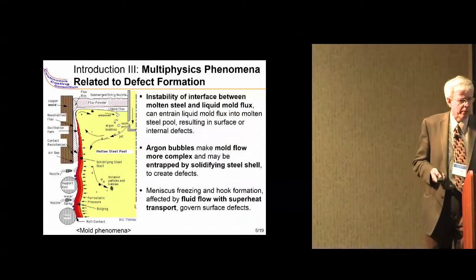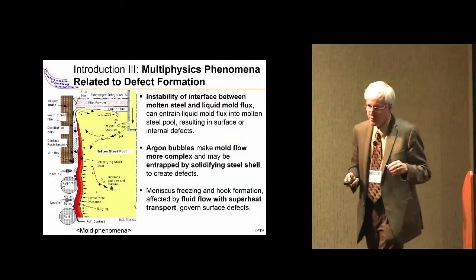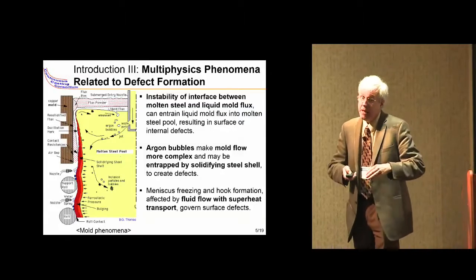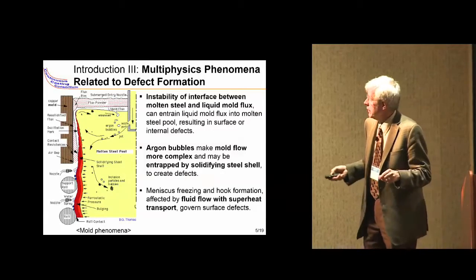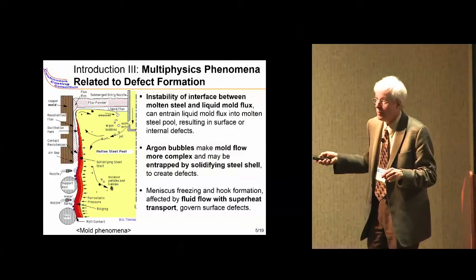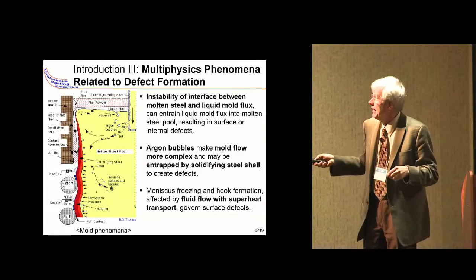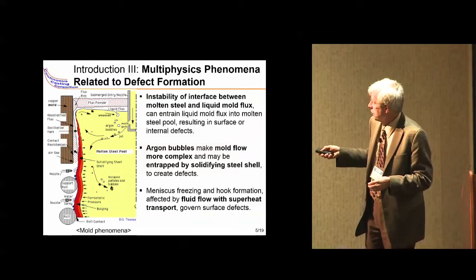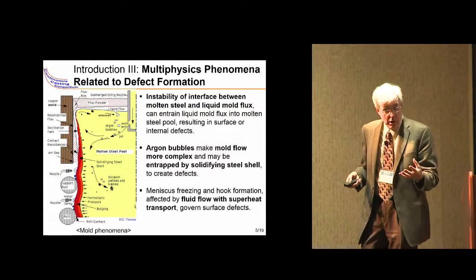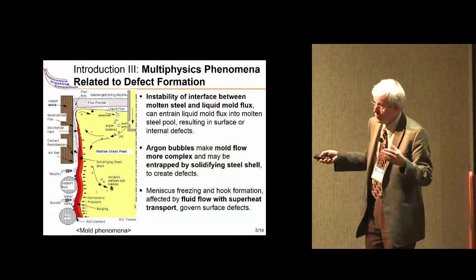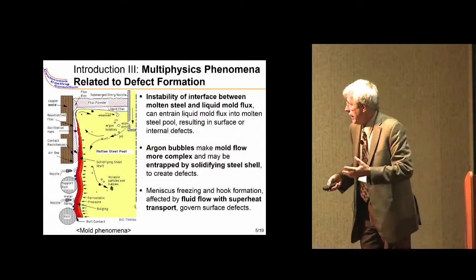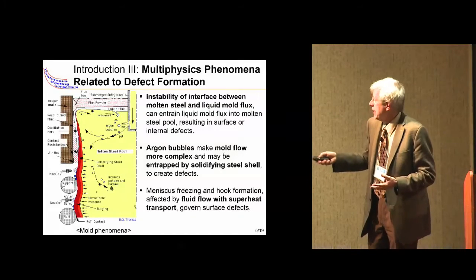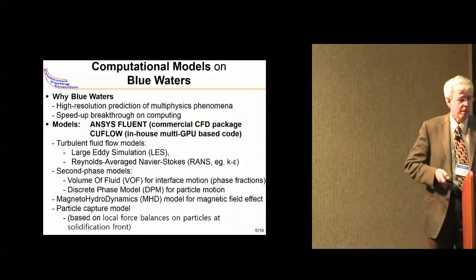Just understanding the steady state flow pattern isn't enough; we have to solve defects. We're interested in transient fluctuations of the surface level which can trap particles and cause surface defects. Gas is injected and these bubbles prevent nozzle clogging, which is good, but if trapped in the product they create defects. The top surface can freeze and the profile can change, another source of defects we'd like to solve.